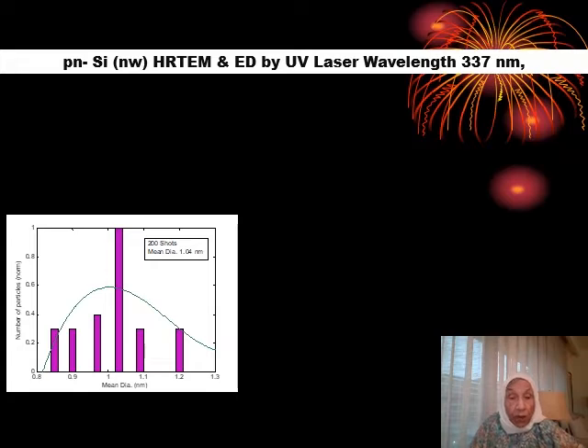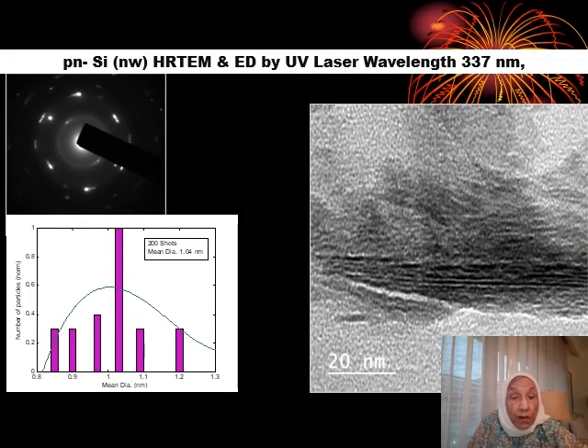So for these conditions, we found that the mean diameter of the rods varies from 0.85 to 1.2 nanometer, peaking at the value of 1.04 nanometer. That is the number of particles against the mean diameter. As you see, it is peaking at 1.04 nanometer. This is the electron diffraction spectrum, which confirms the crystalline structure formed.